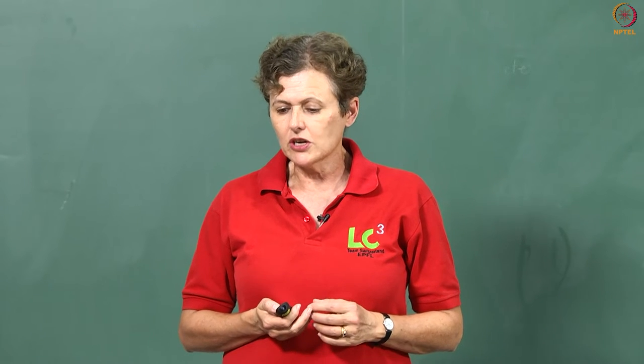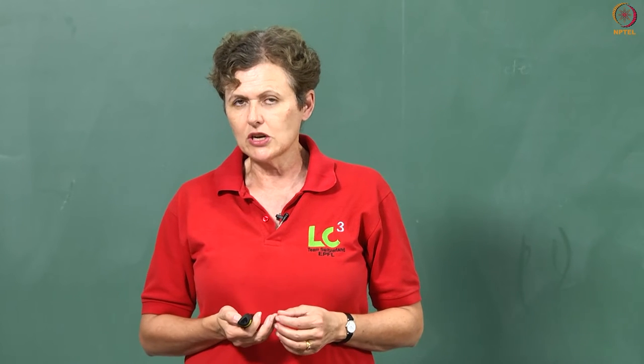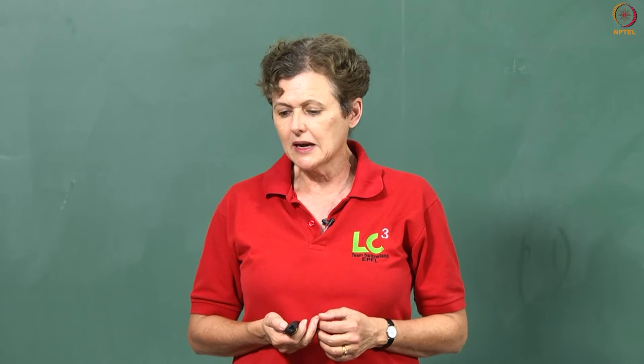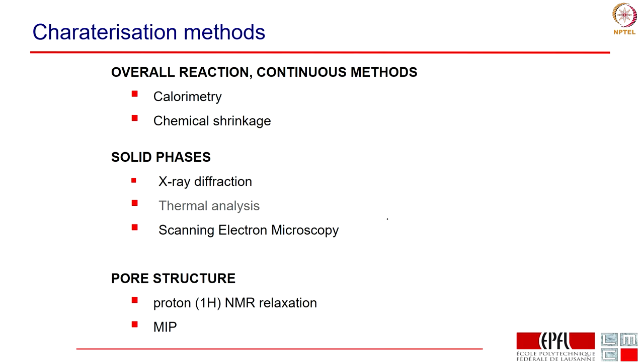That is the hydration reaction, where what we are interested in is the phase content and distribution, how the phases form, the kinetics, etc. Microstructural characterization can also be used for looking at durability aspects — how the microstructure is affected by the environment and what the mechanisms responsible for degradation are. In terms of characterization methods we can take it in three parts: continuous methods that follow the overall reaction, methods to look at the solid phases such as x-ray diffraction, thermal analysis, and scanning electron microscopy, and techniques to look at the pore structure.